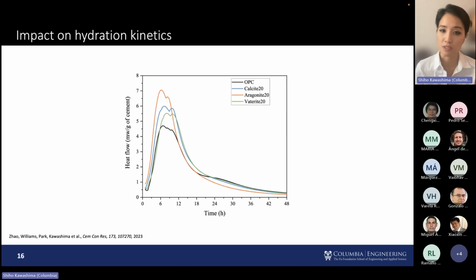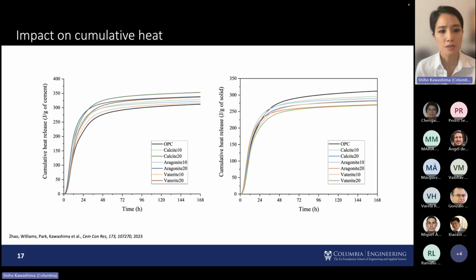And we can likely just attribute that to the increase in specific surface area, where they have more surface area for CSH nucleation to occur. We also looked at cumulative heat release. On the left, it's again normalized with respect to cement. And here it's interesting because over time, initially the aragonite has the highest cumulative heat release, but then it crosses over around 24 hours, where calcite then exhibits the highest cumulative heat release. I don't include the results here, but we found that calcite actually has the most reactive surface. And so although aragonite has higher surface area, calcite has the most reactive surface. And so that may be coming into play at longer time periods.